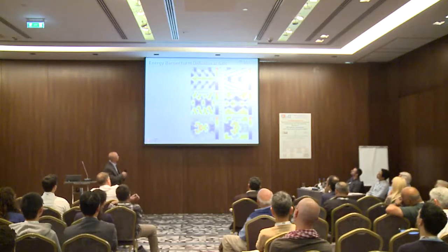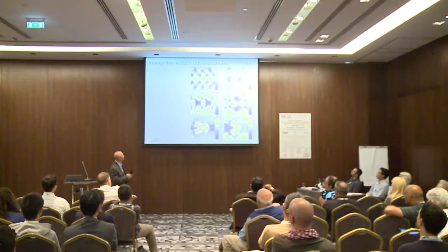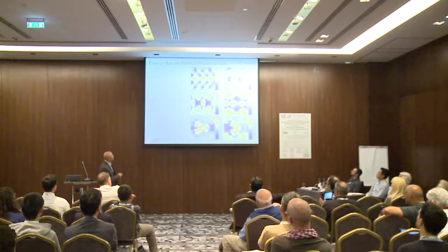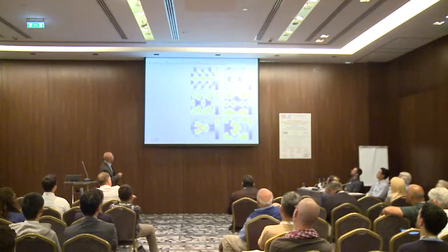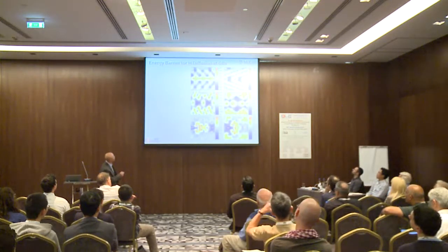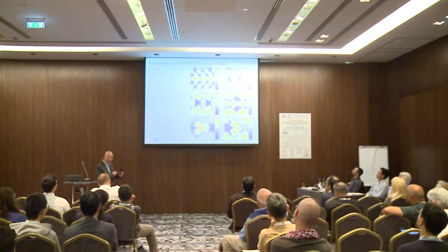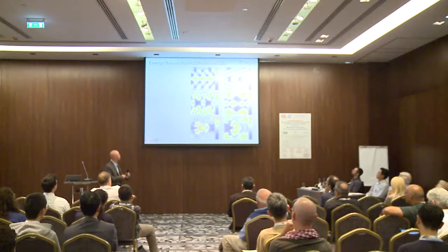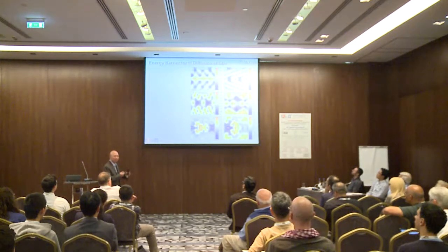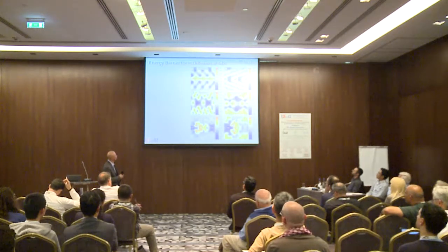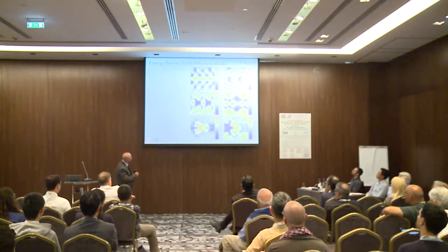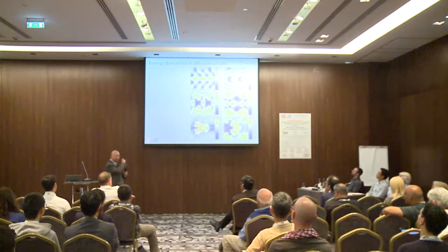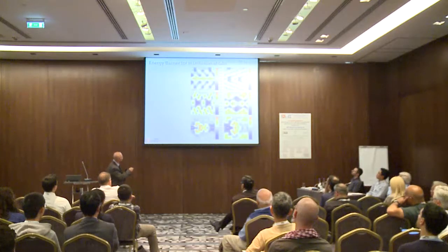I forgot to mention that those blue regions correspond to the low barrier, while the red correspond to the high barrier. For the first two cases, they are very high symmetry grain boundaries. Compared to the bulk, there's some slight difference, but overall the barrier mapping is quite close. So in these two cases, you would expect similar diffusivities through the grain boundary. While in the second row, you have a connected path along the grain boundary, all blue. The key word here is that you have a connected path through the grain boundary that gives you continuously low barrier along the grain boundary.